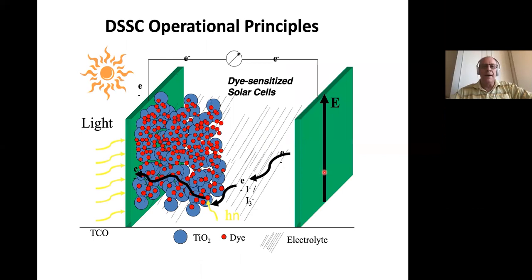We have here our transparent conducting oxide, our contact. We have our TiO2 nanoparticles, typically 20 to 30 nanometer in diameter. It forms this porous sponge where we have then the dye molecule, the red spots on the surface. We have the electrolyte, and typically it's iodide, triiodide as our redox couple. And then we have the plus, the cathode, as we say, on this side.